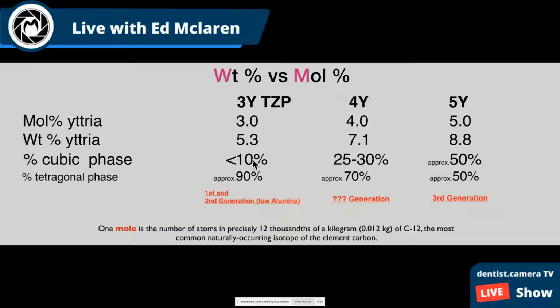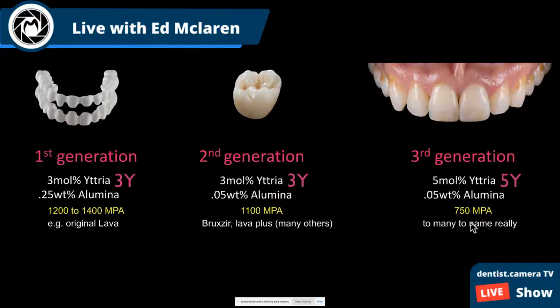And zirconia exists in 3 different crystal shapes: tetragonal, cubic, the fake diamond, the translucent stuff, and then this monoclinic crystal, which we'll talk about. So 3 different phases, 3 different types of zirconia. Think of it that way. All right, so when you increase to 5Y, or 5% of the molecules yttria, you shift the phase from mostly tetragonal to 50% cubic phase. We get super translucent stuff. I'm going to back up for a second here. We do give away something though. We lose quite a bit of strength. We go down to 750, but that's pretty strong.